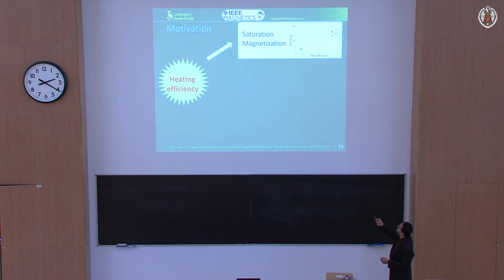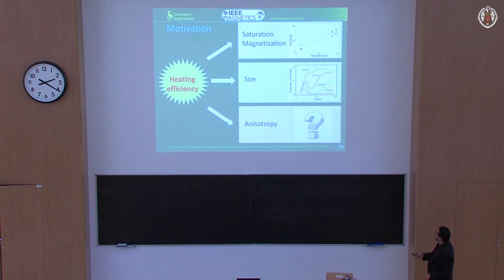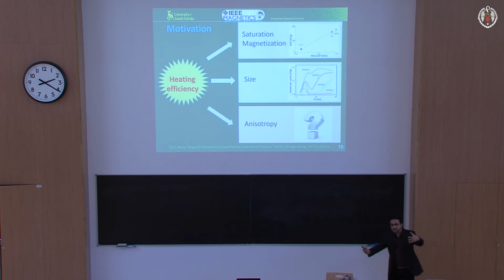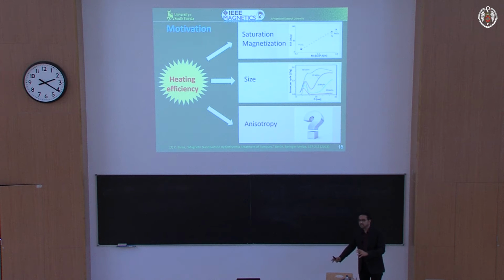But if you look at the SAR value, iron oxide is low compared to iron cobalt. So obviously there's a problem here. We'll see how we can tackle this. There's some size dependence, but anisotropy is an open question. Remember that you can change the anisotropy and change the shape of the hysteresis loops, which will have an effect on the area in the loop and dissipation. So nobody really took the effort to systematically study this. Again, that's the reason I'm giving my talk here. We were one of the first groups that started looking at correlation between anisotropy in nanoparticles directly with the SAR.